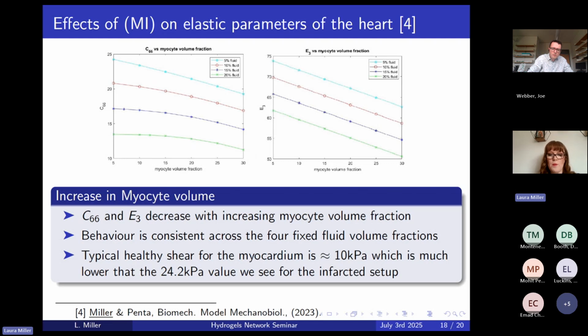Typically, the healthy shear for the myocardium is approximately 10 kilopascals, which is much lower than the 24 that we're seeing for the infarcted setup. Say, that 24 is probably somewhere about here. So this is when the perfusion is very low, when the vessels have become very constricted and the myocytes have died, and the scar tissue is coming in. But obviously with that swelling of the surrounding ones, we are bringing it down if we remain at a 5% perfusion. By increasing our perfusion, we can bring it down until, with the bulk 20% perfusion, we can almost return to that typical healthy shear that the heart would like to have in those myocytes.